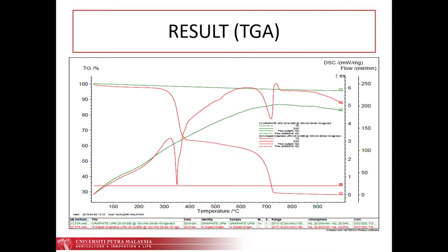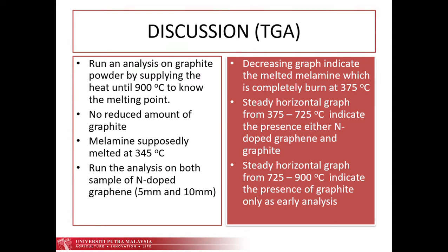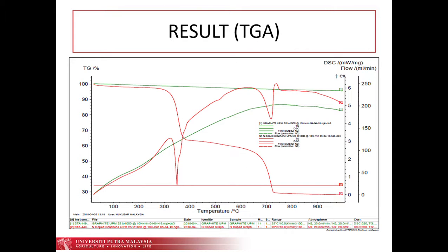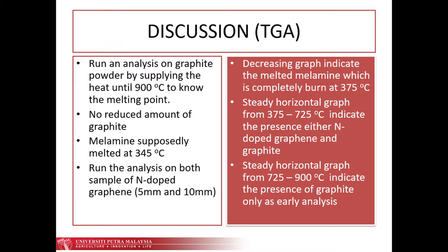So, to justify there is nitrogen-doped graphene in our product, the TGA analysis is conducted. First, initially we run the graphite. We heat until 900 degrees Celsius, but it seems that graphite does not reduce until 900 degrees Celsius. Then we run the nitrogen-doped graphene until 900 degrees Celsius and it has reduced elements from the graph. As we know, the melamine will melt at 345 degrees Celsius. Thus, as we can see, from 300 degrees Celsius until 375 degrees Celsius, there's a decline in the graph that shows that the melamine is completely burned.